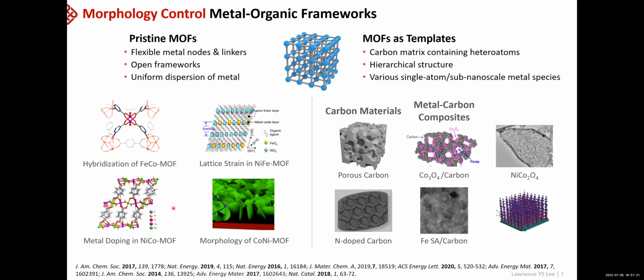One of the first materials that we were interested in, to pick two metal species that can combine or influence each other so that together they can go up to the top of the volcano plot, is metal organic frameworks. These are made of metal nodes and linkers, and they are open frameworks with uniform dispersion of single metal species. So they are used for combining two different metals like nickel and iron, or cobalt and nickel. They can also be used as a template, as we saw in the previous talk, to produce a carbon matrix containing metal atoms, so that they can be used to produce single atom matrices.